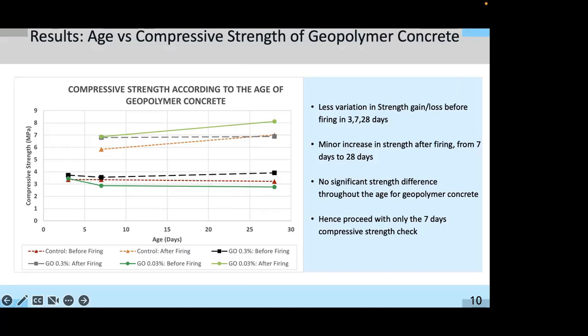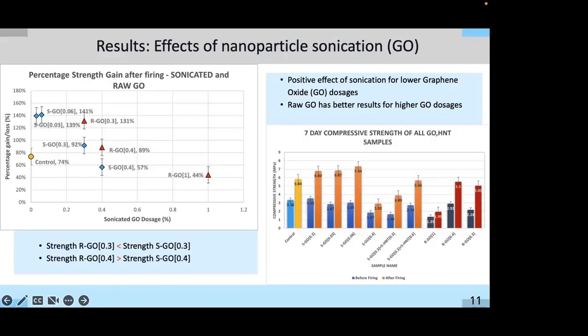So comparing it with the different ages, you can see that there is some increase in strength from 7 to 28 days, even after the elevated temperature performances. So as I mentioned to you, this is the sonicated version versus untreated GO, graphene oxide. And we do see that for the lower graphene oxide dosages, the sonication does have a positive effect.